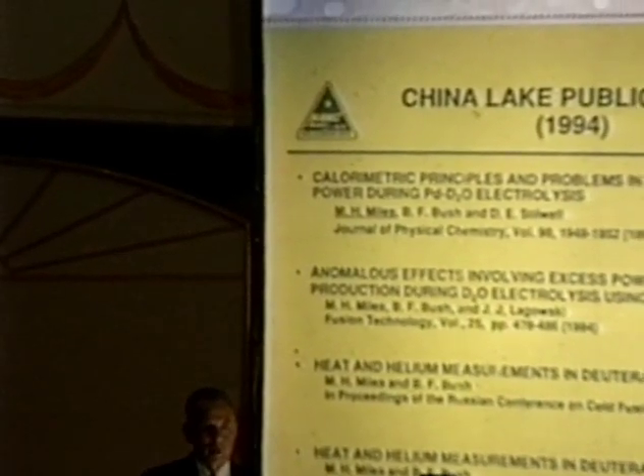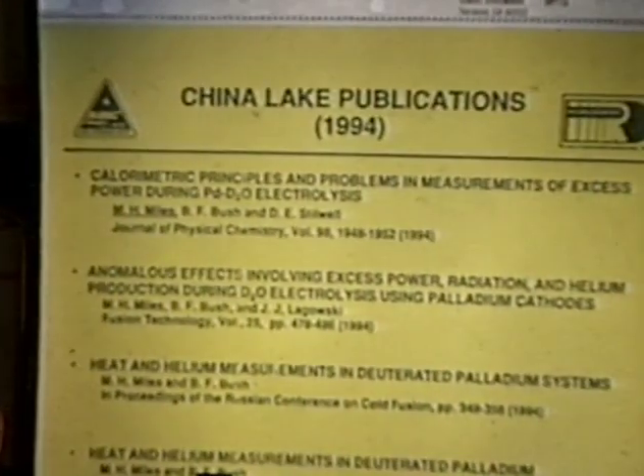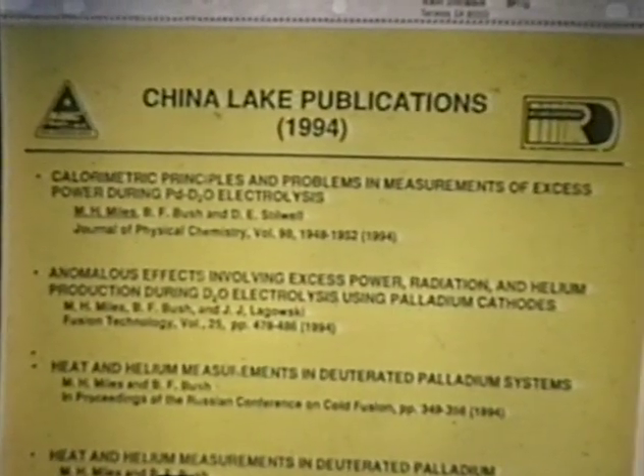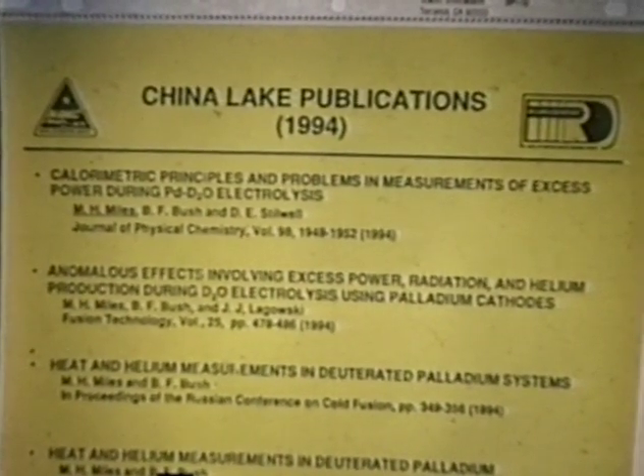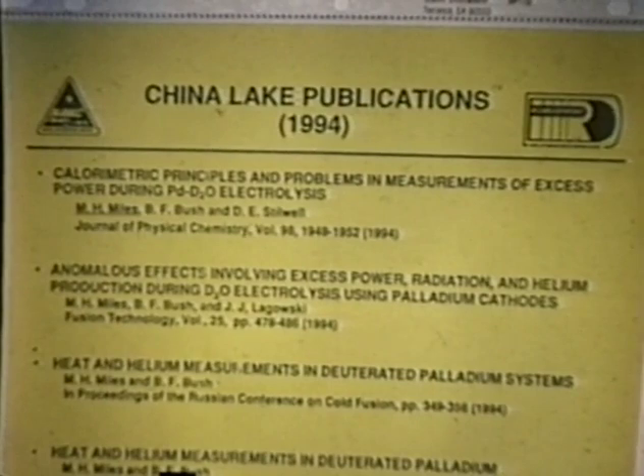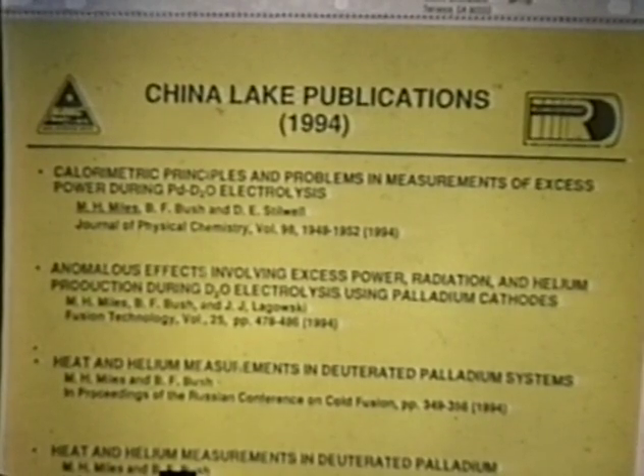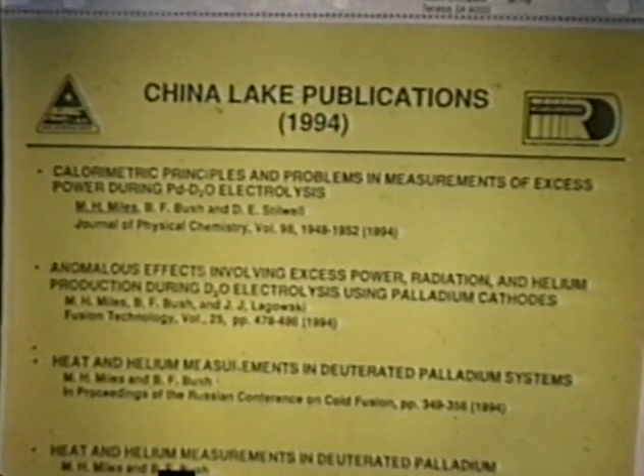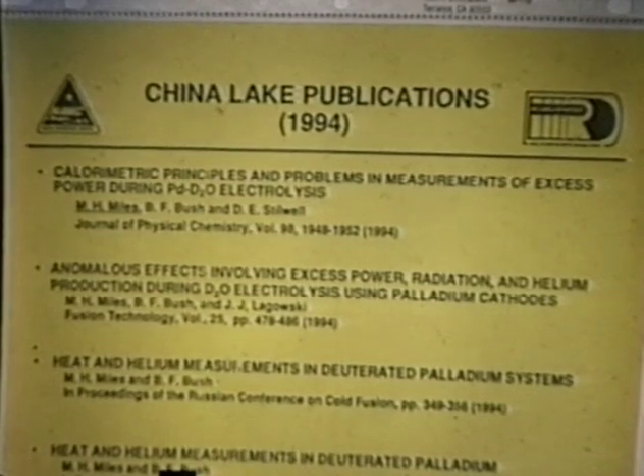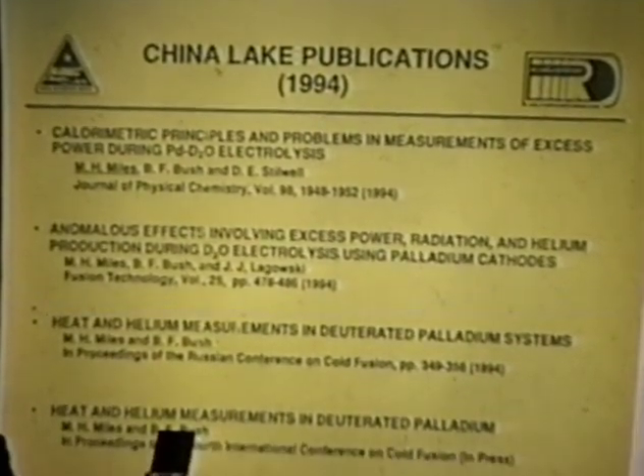Okay. I hope I get a chance to write a rebuttal to his paper because that's easy to answer. When we first reported that, we did not know what our detection limit was. We did not have good data on our detection limit. We were reporting it as 0.1 part per billion at that time. But since then, we've measured the background of our system in metal flasks, and we know that our background is around 4 parts per billion. So 0.1 part per billion could not have been our detection limit, because our background is 4 parts per billion. And so we know what our background is today.